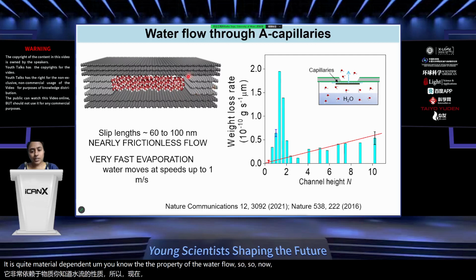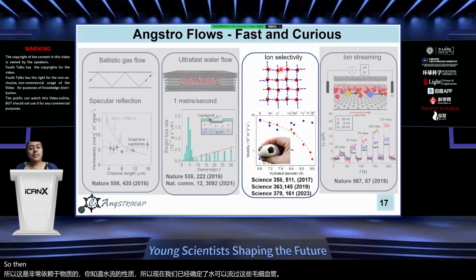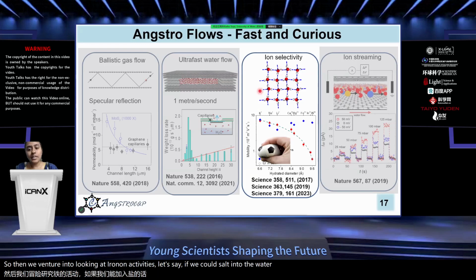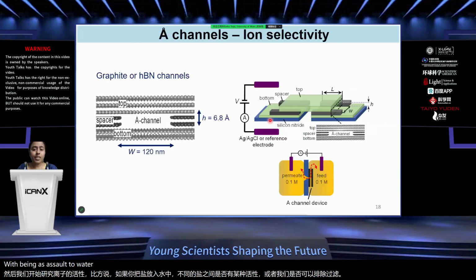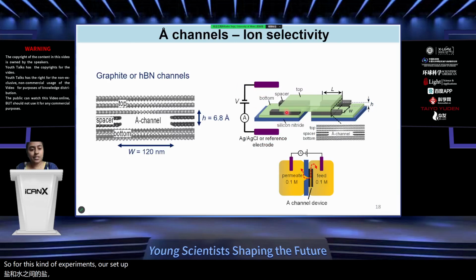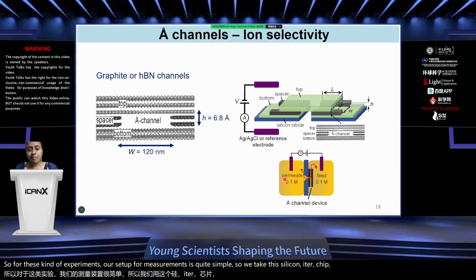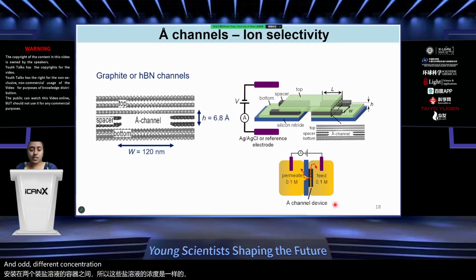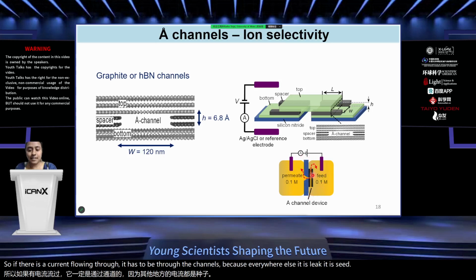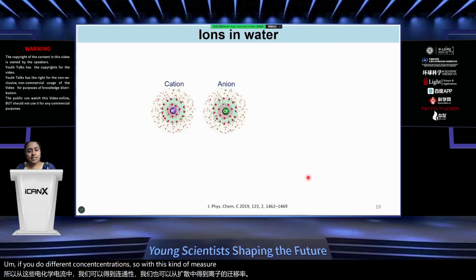So now that we established that water can flow through these capillaries, we ventured into looking at ion selectivities. Let's say we put salt into the water: is there any selectivity between different salts, or can we filter out salt from water? For these kinds of experiments, our measurement setup is quite simple. We take this silicon nitride chip and mount it between two chambers which contain the salt solutions. These salt solutions can be of the same concentration, or of different concentrations if it is a diffusion experiment. Then we measure the currents through these electrodes. If there is a current flowing through, it has to be through the channels, because everywhere else it is sealed. So from these electrochemical currents, we can get the conductivity, and we can also get the mobility of the ions from the diffusion if we put two different concentrations. With these kinds of measurements, we measure the ion flows.